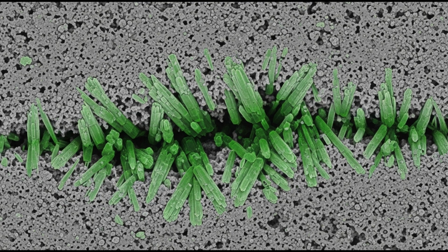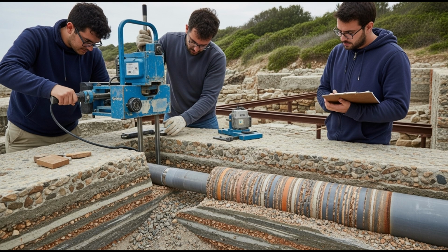The seawater improves it. Documented evidence: core samples from Portus Cosanus, a Roman harbor on the Tuscany coast built in the 1st century BC, were analyzed by UC Berkeley and Italian researchers and published in 2017 in American Mineralogist. They found extensive tobermorite formation, with crystals growing in cracks, filling voids, and binding the matrix tighter.